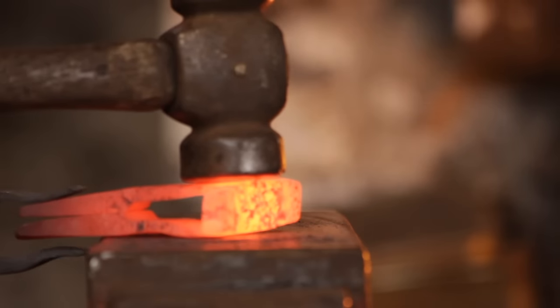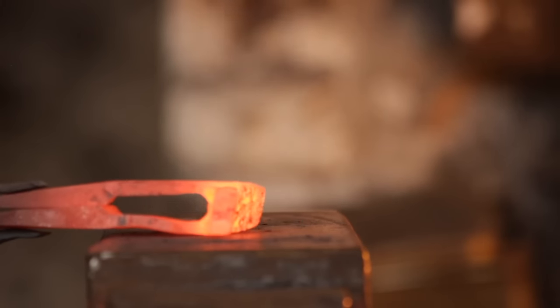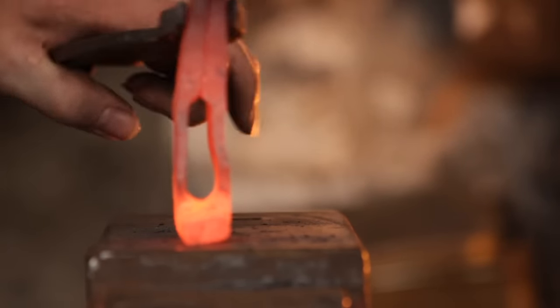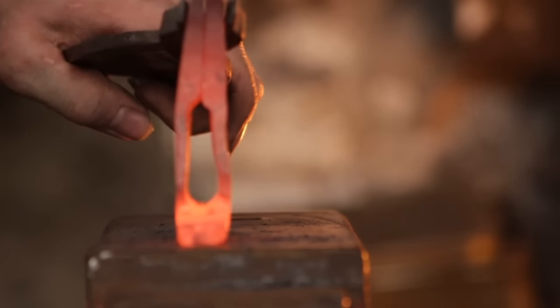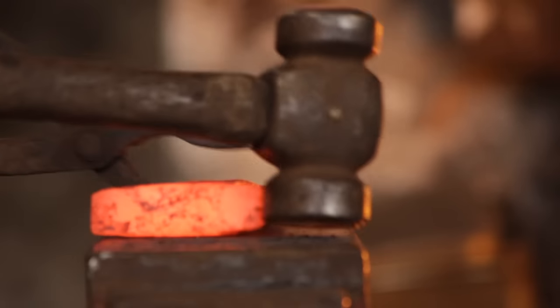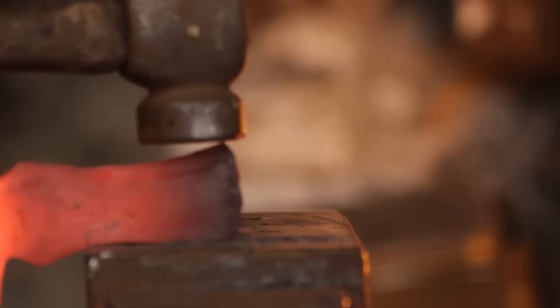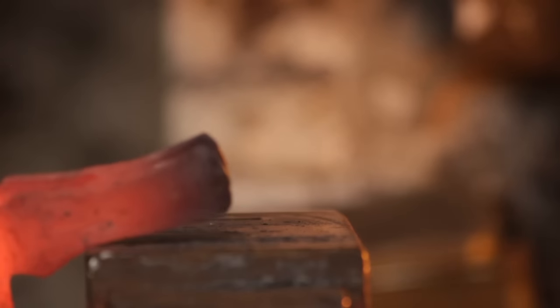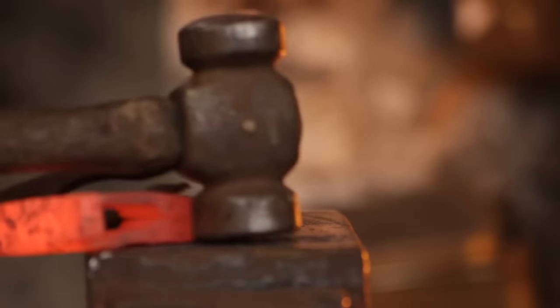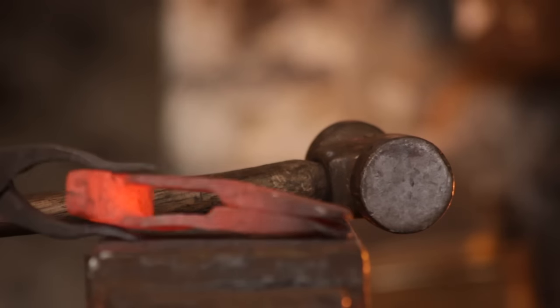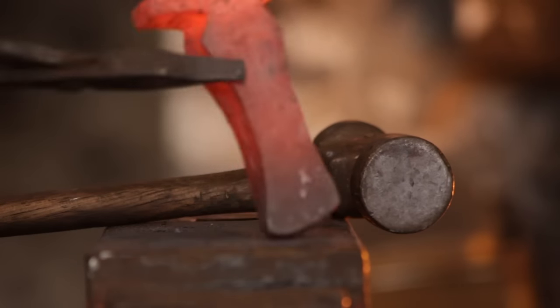As you can see the tongues of the pole are kicking back a bit and that caught me a little bit by surprise. I should have seen it coming really but it's not the end of the world because it'll dress out with the drift inside afterwards. Make sure both halves meet properly. There we go, top half of the axe head.